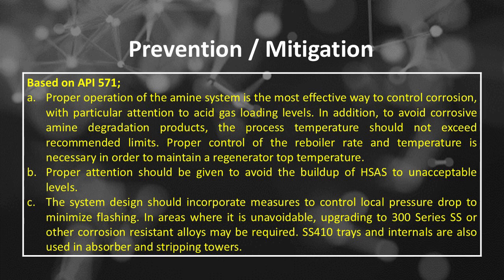Number A, proper operation of the amine system is the most effective way to control corrosion, with particular attention to acid-gas loading levels. In addition, to avoid corrosive amine degradation products, the process temperature should not exceed recommended limits. Proper control of the reboiler rate and temperature is necessary in order to maintain a regenerator top temperature.